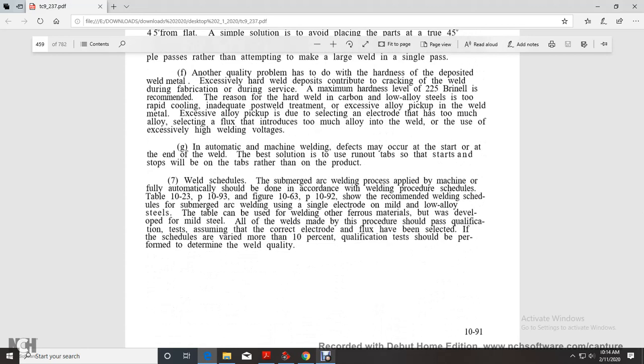Extremely hard welded deposits contribute to cracking in the weld during fabrication and during service. A maximum hardness level of 225 Brinell is recommended. The hard weld of carbon and low alloy steel is due to too rapid cooling with inadequate post-weld treatment, and excessive alloy pickup in the weld metal. Excessive alloy pickup can come from using an electrode with too much alloy, a flux that introduces too much alloy into the weld, or the use of excessive high welding voltage.